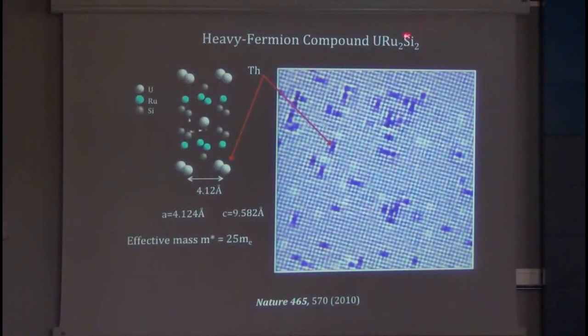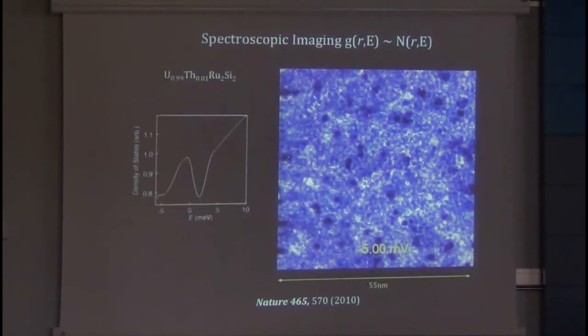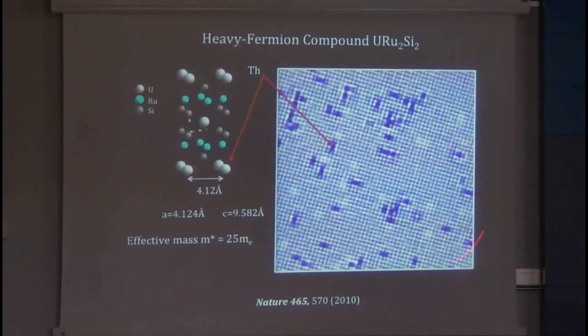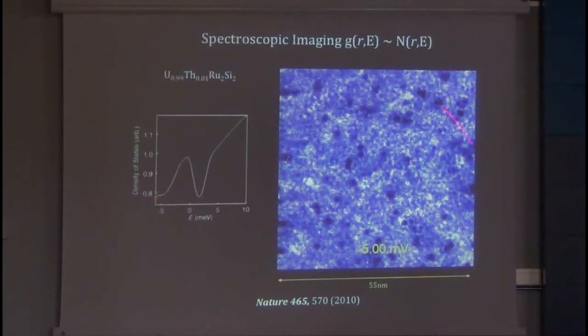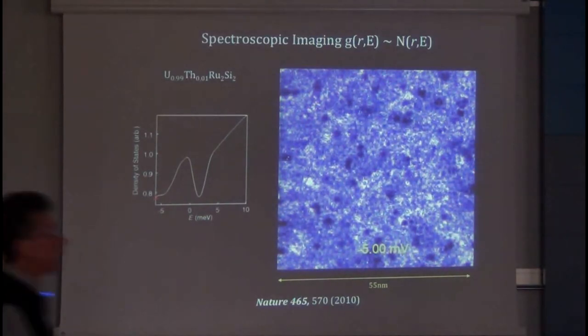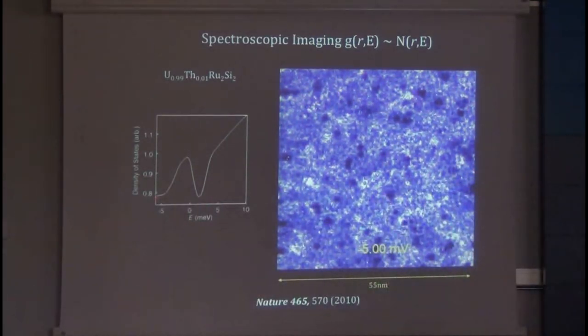The first material we looked at was actually uranium-ruthenium-2-silicon-2. It's a modestly heavy fermion superconductor, which is good for exploration experiments. Because the band is not so flat that you can't follow it. It's just about right to detect it. So on those compounds, the surfaces are very beautiful. These sites here are thorium atoms substituted on the uranium site to produce the scattering that we need. And then on the surface of those compounds, we were able to image the heavy Fermi wave functions.